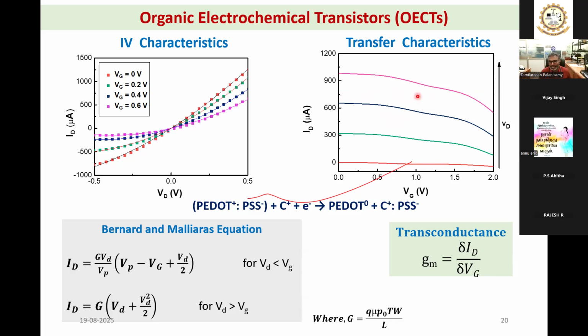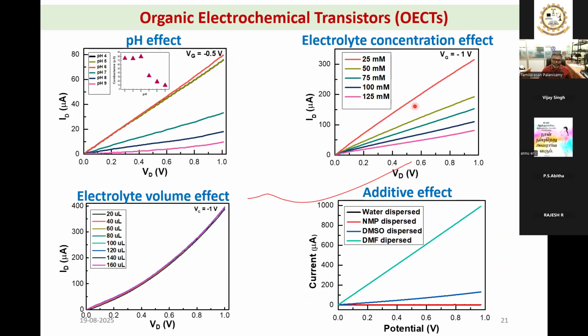Very parallel straight line, parallel to your x-axis. But what you are seeing is there is some change. Where we see the top curve, there is a clear change. It means that the potential applied to the gate is actually modulating the current in the channel. So that is what we have achieved. So already we have seen here, and the same concept in a different plot has been concluded here. With the transfer characteristics, it is once again reaffirmed. And then we have fabricated the OECT successfully.